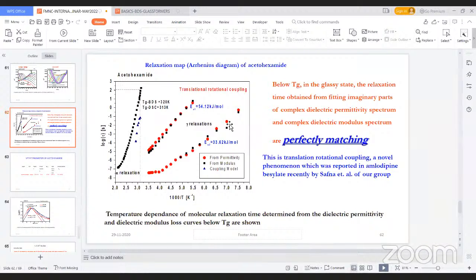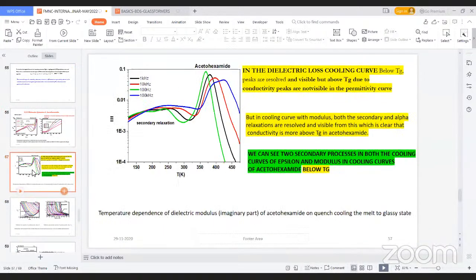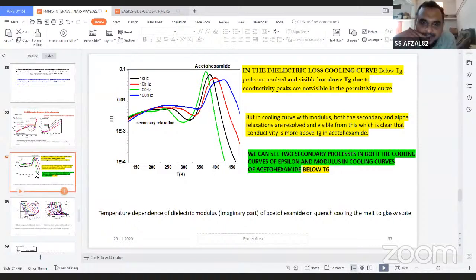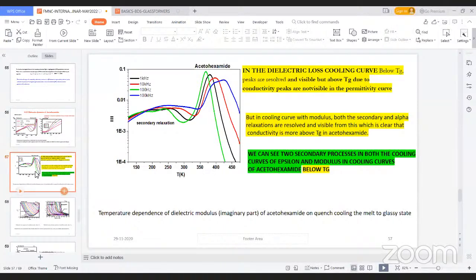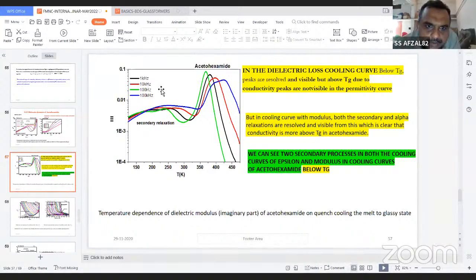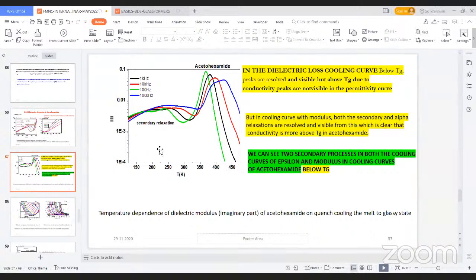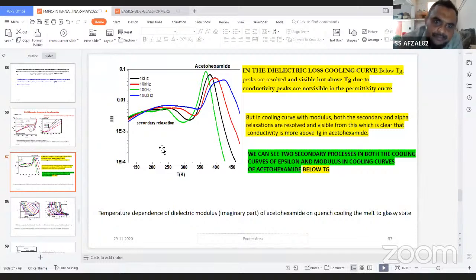Then I need a clarification from slide 57. What is the variation? What is the effect of this frequency? The frequency is fixed and the sample is cooled. Is there any systematic variation? No. This corresponds to a relaxation process. That is why we are getting a peak. But in the secondary region, at lower temperature, we are getting two peaks, which correspond to two secondary relaxations.